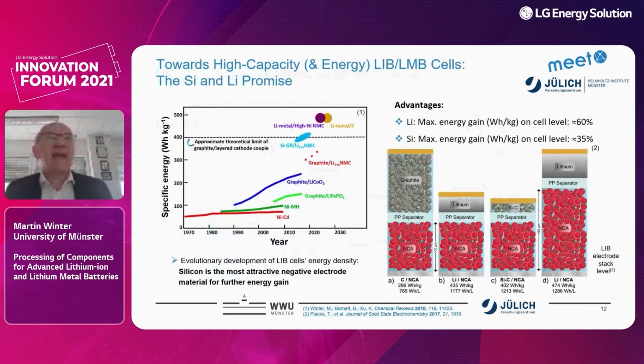And this leads us on the anode side to two electrode materials which are in the focus of mostly everybody in our field now: the silicon anode for the lithium-ion configuration and the lithium anode for the lithium-metal battery configuration. And if we compare them to the graphite-based lithium-ion batteries, we see that silicon is giving us higher specific energy, and lithium metal, again, even higher specific energy.